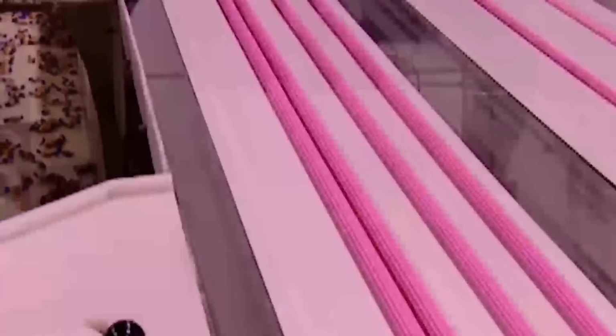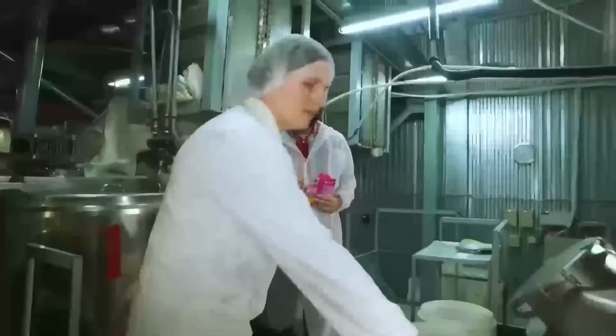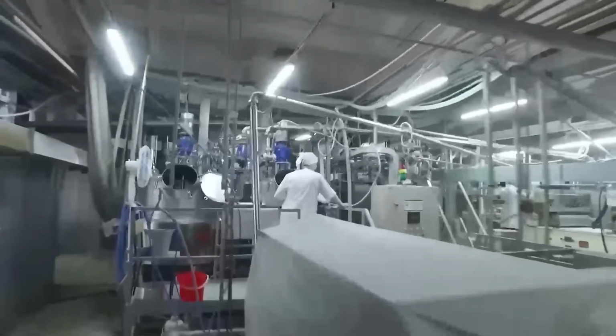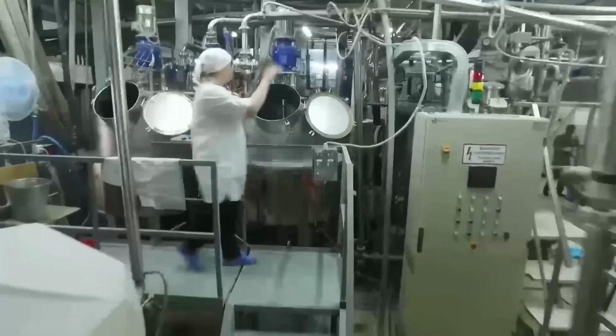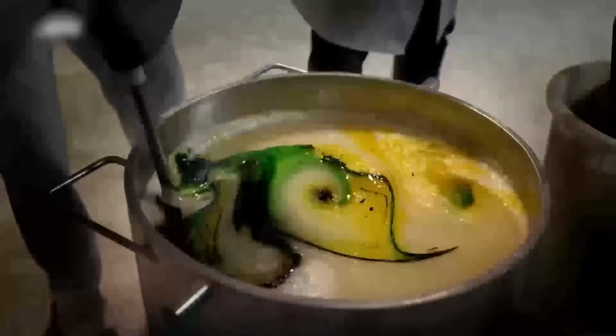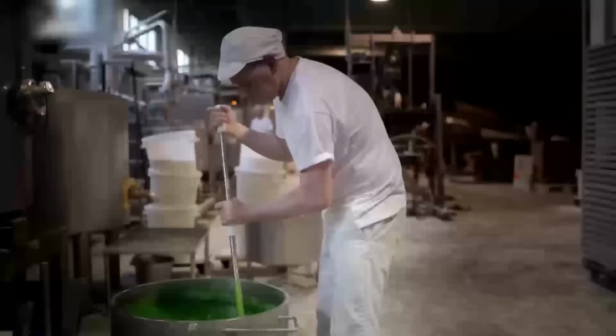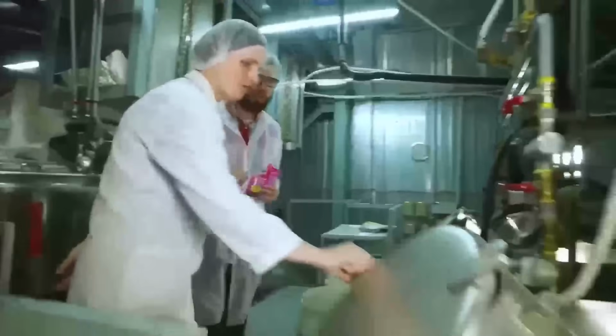Depending on the size of the batch and the recipe, the blending cycle can last anywhere from 45 minutes to several hours. The mixer itself is equipped with internal thermocouples to continuously monitor the temperature of the mass, which is maintained between 60 degrees Celsius and 90 degrees Celsius. Too low and the materials won't melt and blend. Too high and thermal degradation could occur, affecting the safety and performance of the gum. Operators observe the process through viewing ports and rely on torque readings and viscosity data from the mixer's internal sensors to determine the exact moment the gum base is fully homogenized.